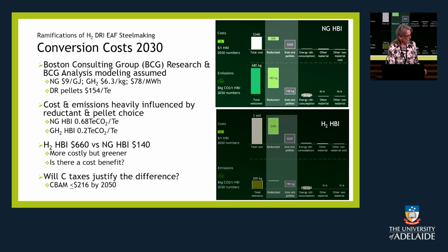This is a conversion cost analysis done by Boston Consulting. Very quickly, they used natural gas at $9 a gigajoule, hydrogen at $6.3 a kilogram, electricity at $78 per megawatt hour, and DRI pellets at $154. Yes, natural gas HBI is down at 0.68 tons of CO2, and the green hydrogen is down at 0.2, but you've got a $660 cost for the hydrogen DRI versus $140 for the natural gas DRI. So the question becomes: are the carbon taxes going to justify the difference in the cost of making hydrogen?